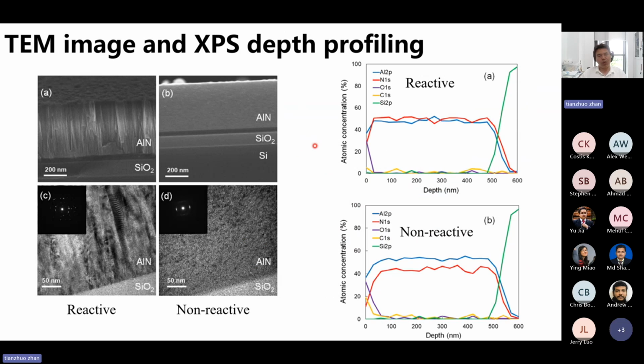And so this is because we observe the TEM image and also do characterization by XPS depth profiling, and we found the crystalline quality of the aluminum nitride thin film is very poor. The non-reactive sputtering method gives a totally amorphous phase, and for the reactive sputtering one, only very small crystallites can be observed, and the quality is very poor. So this results in the very low thermal conductivity of the aluminum nitride thin film. So that means aluminum nitride thin film deposited by sputtering is not a good candidate. So we need to improve the thermal conductivity of the heat guide layer.